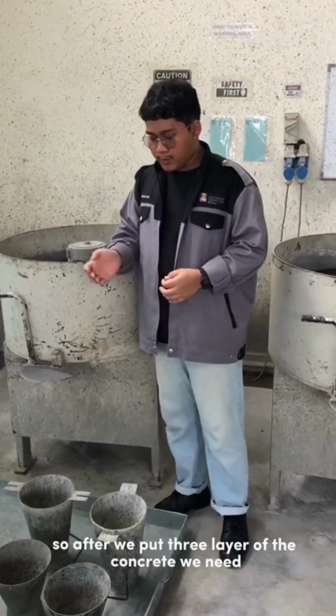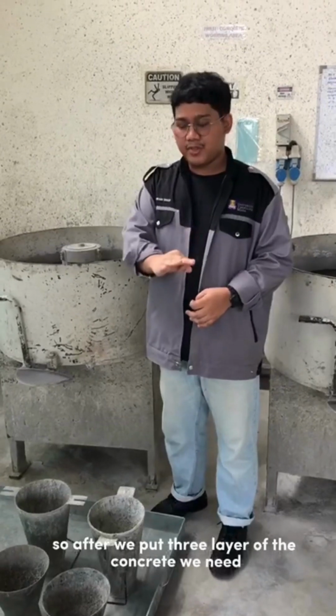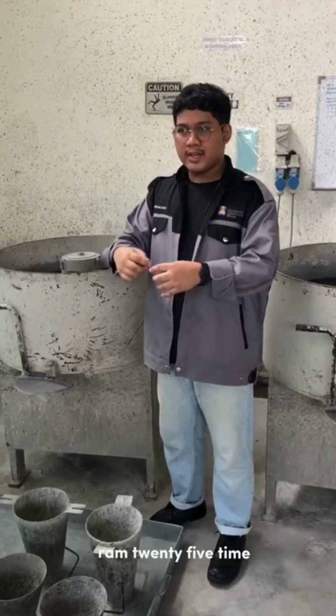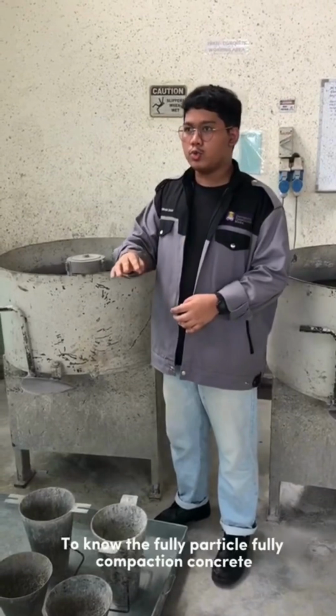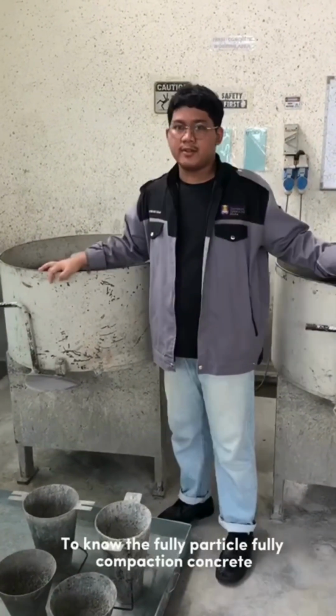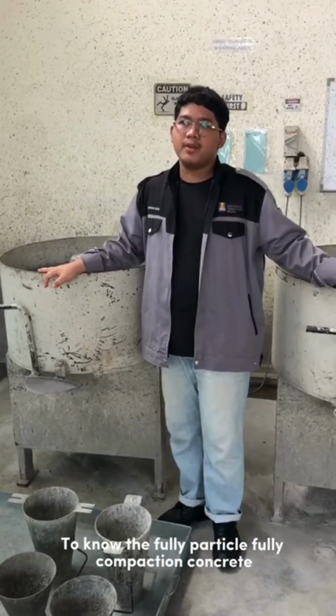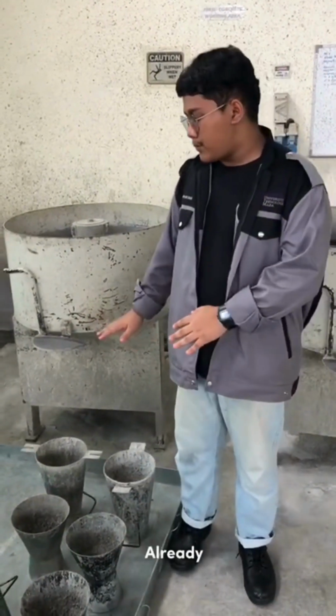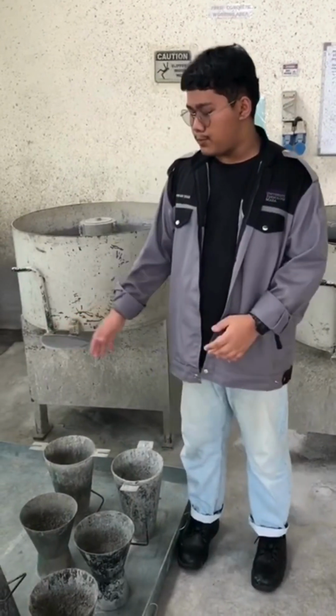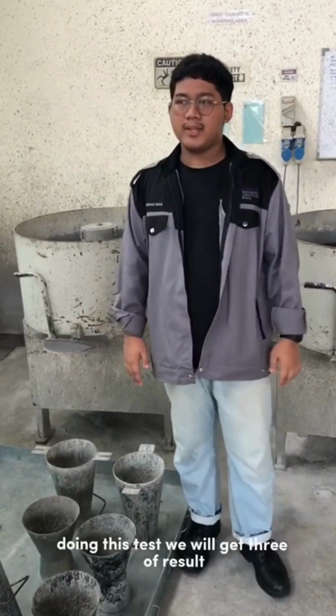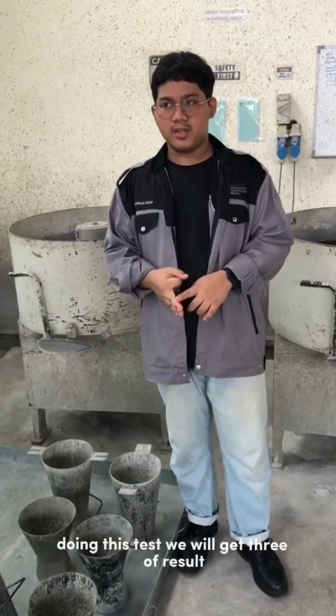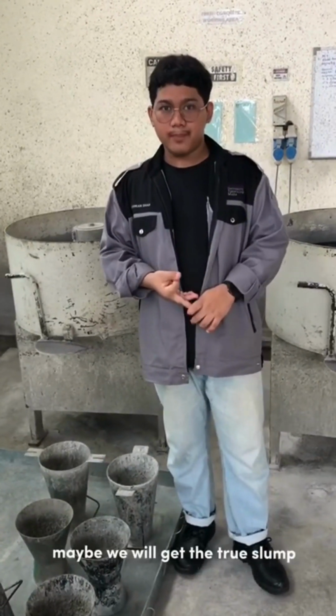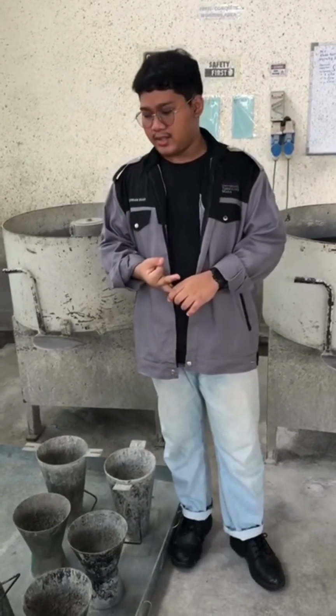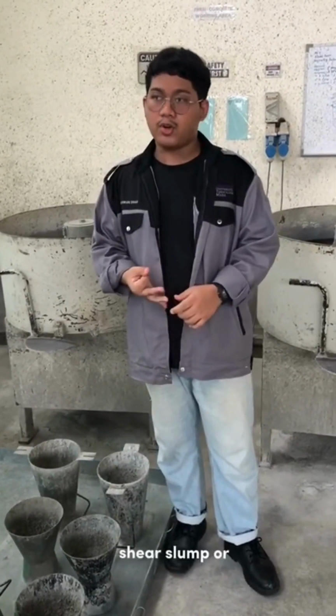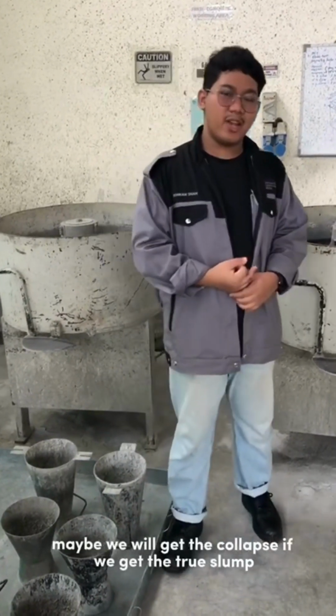After we put in 3 layers of concrete, we need to ram 25 times to get fully compacted concrete. After doing this test, we will get 3 possible results. Maybe we will get the true slump, maybe the shear slump, or maybe the collapse.